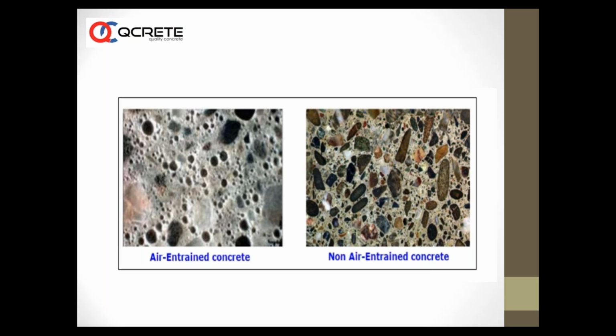So a lignosulfonate based admixture in combination with some air entraining admixture will work as a waterproofer, complying to IS 2645. Another very important usage of air entraining admixture is that, let us say you have a very harsh sand, zone 1 sand, bad sand, and you want to make concrete with bad aggregates. Okay, a lot of flaky materials are there. In such situations, air entraining admixture holds the concrete together, increases the pumpability, and makes the concrete look like butter, easily pumpable, placeable.